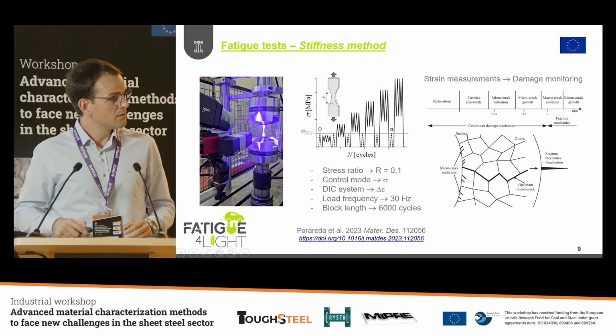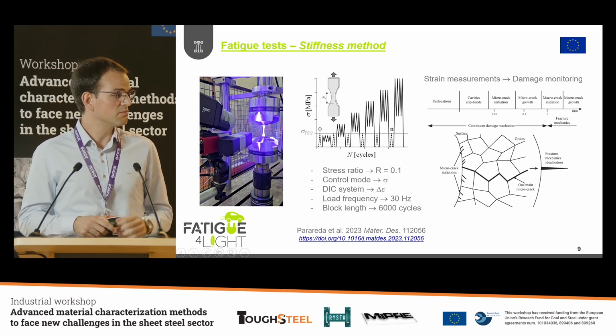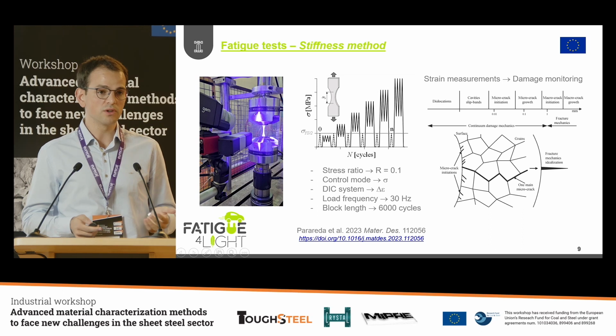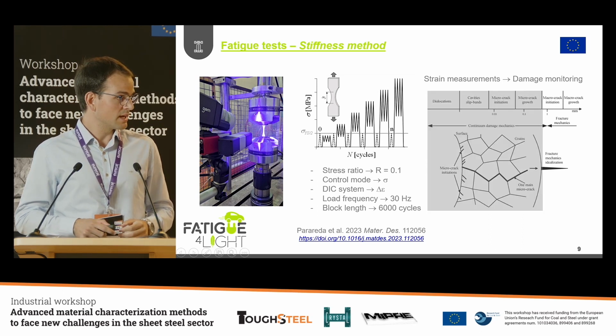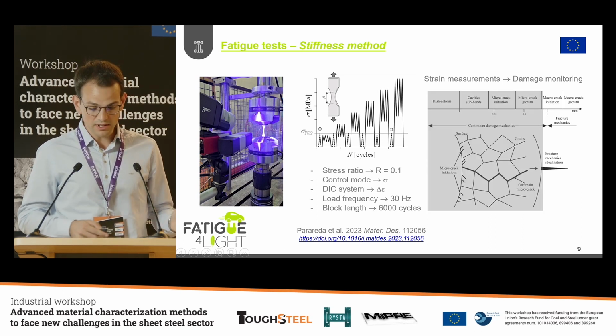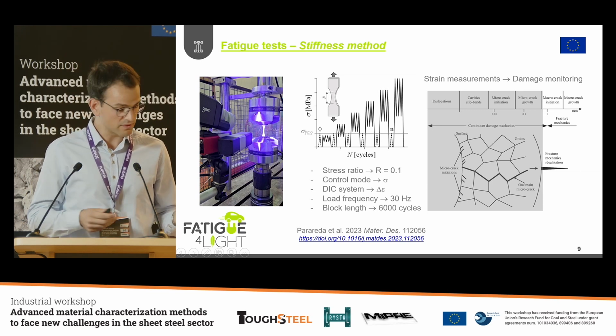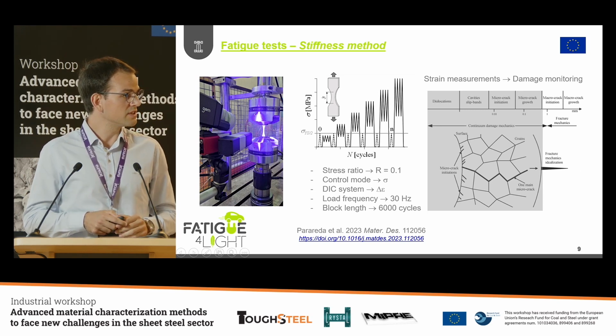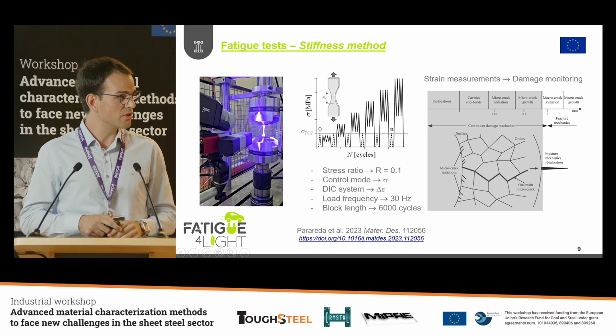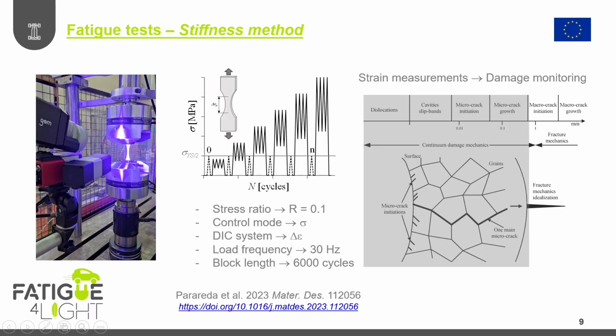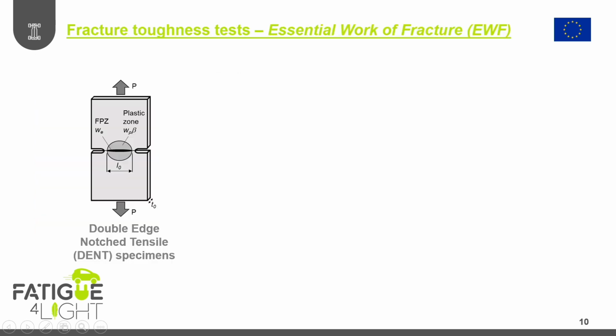And by using this data, we can rapidly assess the fatigue limit of the material and have an idea of what's happening, or which will be the effect of these different defects on the fatigue resistance. In this case, we are always focusing on this incipient fatigue damage, in this continuum damage mechanics regime, and we are just skipping the part of fracture mechanics when we have a large crack and the crack is only propagating.